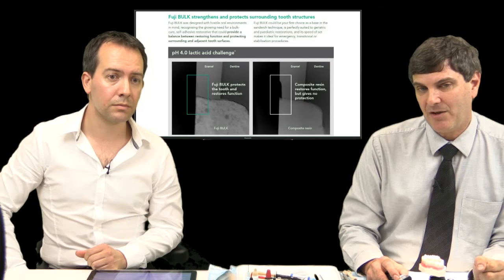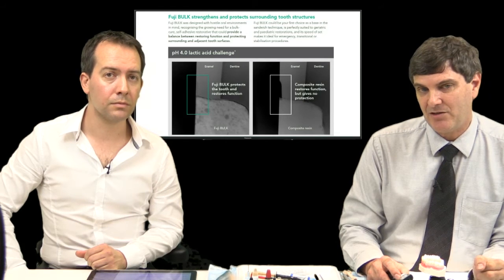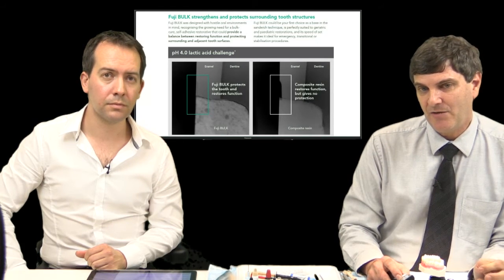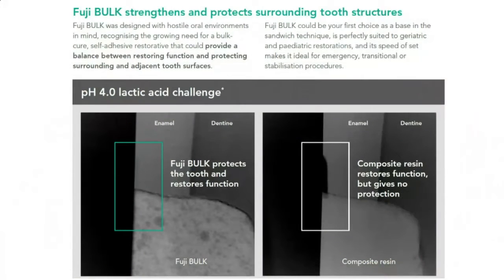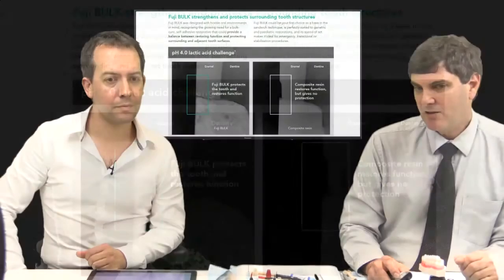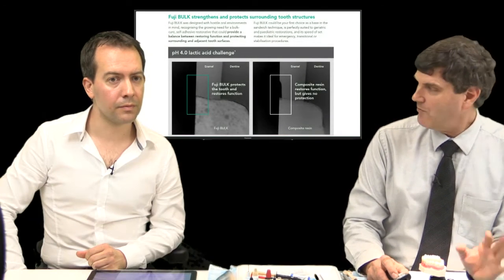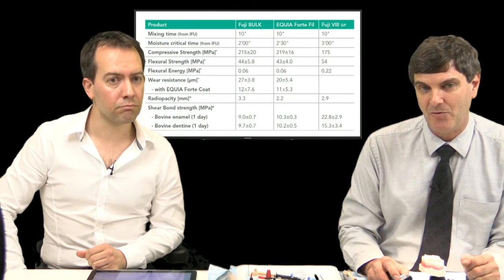And there's some data coming out, and again, this is manufacturers' information, that a lactic acid challenge where you've got pure composite resin, which is on the right-hand side, results in some demineralization of the adjacent enamel. But when you put the Fuji Bulk in and expose it to the lactic acid challenge, you don't get any demineralization. So there's more research to be done on this, but I think we've got some great products out there, and there could be more and more.